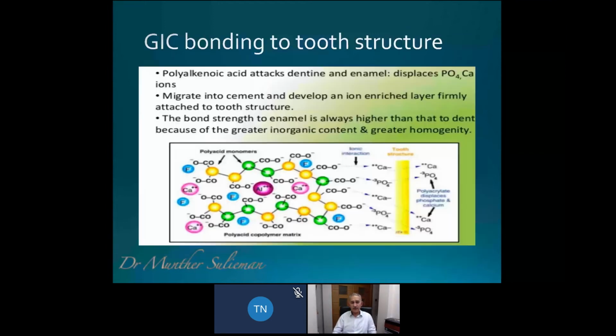When we look at the glass ionomer bonding structure, well, that's much easier, much better. It's basically a polyalkenoic acid that attacks the dentine and the enamel, displaces the calcium and phosphate ions, and there's also migration of ions the other way from the glass, things like strontium and fluoride ions, into the tooth substance, and it produces a chemical bond, which is a very, very strong bond. Obviously, stronger to enamel than dentine, but nevertheless, it is a very, very strong bond. So that's a true chemical bond.